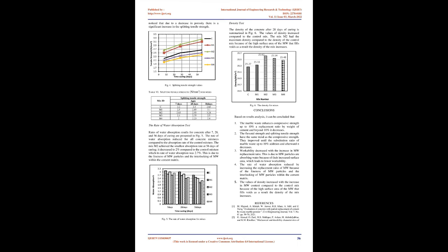The higher the replacement rate of MW, the lower the slump value. This decrease in the slump values is due to the MW particles absorbing water because of their increased surface area, which leads to lower workability. Hardened concrete. Compressive strength test. The obtained values of concrete compressive strength according to the different percentage MW are summarized in Table 4 and Fig 2. The higher the percentage of marble replacement, the higher the compressive strength, up to 10% replacement ratio. The results revealed the highest compressive strength for mix M2.